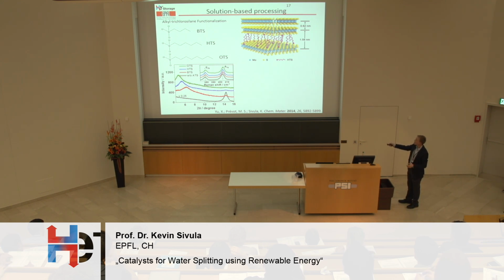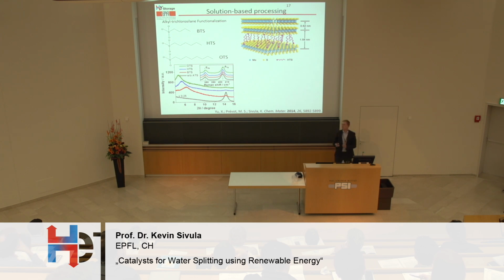While our standard material, a control material, exhibits a restacking, which shows a peak here at about 14.5 degrees, when we apply either the BTS, the HTS, or the OTS, we see almost a complete elimination of this restacking and the formation of a new peak corresponding to an expanded restacking of our molybdenum sulfide. And thankfully, that expanded restacking matches very well with the length of the chain that we use. So for the OTS, for example, the longest chain, we have indeed the smallest diffraction peak, smallest 2 theta, which corresponds to the largest stacking distance. So it's consistent in that respect.